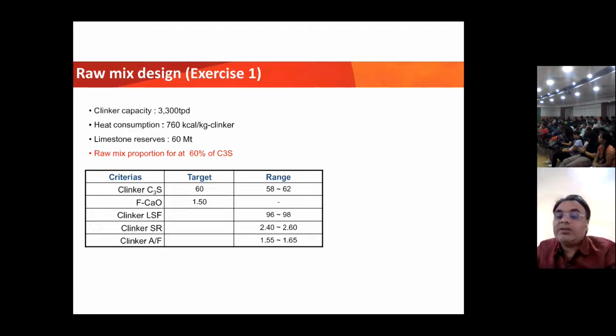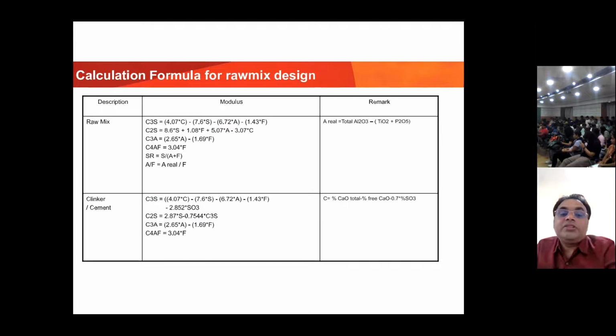Here you can see one term written as free lime, like 1.5. Free lime is the unreacted lime, that is wasted lime. So you have to think that if there is less free lime, then your clinker quality will be good. These are some of the formulas used when you are going for the C3S, because this is very important, so I will not go into the details. This is C3S, C2S, C3A, C4AF, and these are some of the formulas used in that.